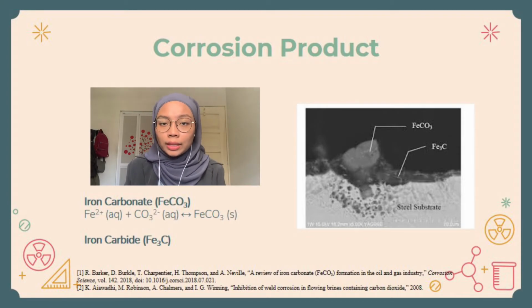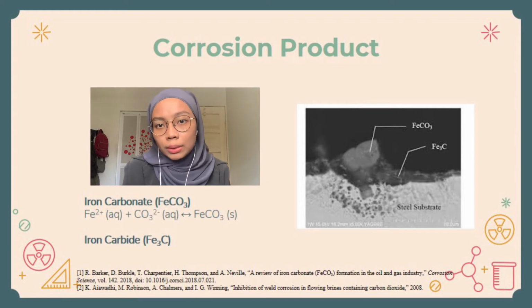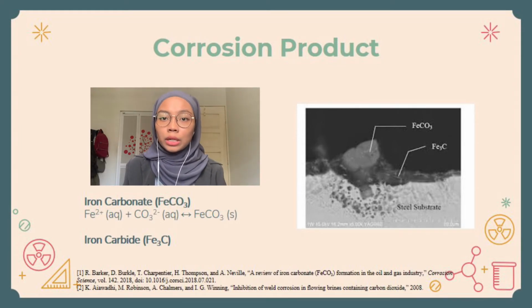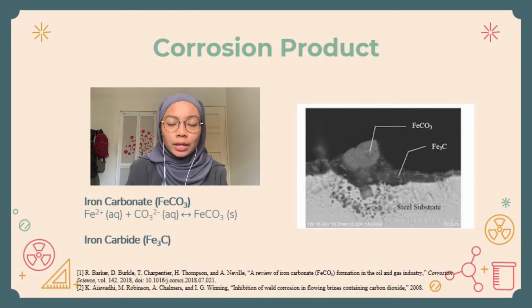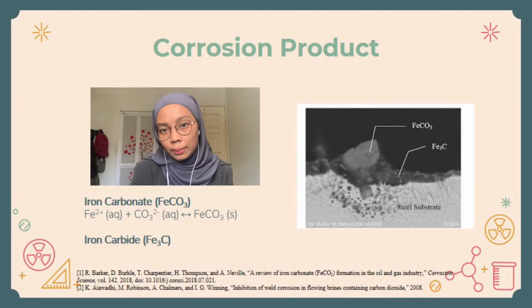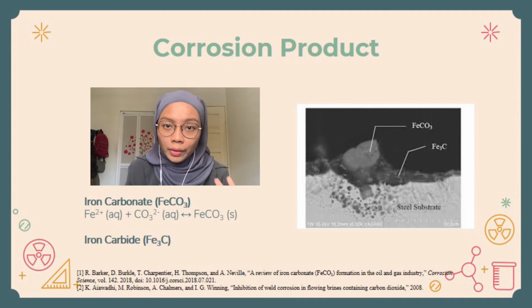Many studies have pointed out that the main components of the film are iron carbonate and iron carbide. In flow systems, corrosion films can observably grow for months without giving protection unless the steel is exposed to stagnant or wet conditions. So for the duration of a few days of stagnation, corrosion products can accumulate on the steel surface and form protective films. Precipitation of iron carbonate on the surface of the metal decreases the corrosion rate by acting as a diffusion barrier for the corrosive species to travel to the metal surface, by blocking a small number of areas on the steel surface and preventing electrochemical reactions from happening on the surface.